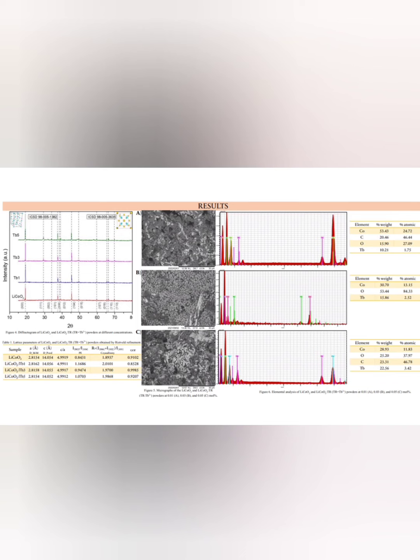According to the results obtained, X-ray diffraction was performed to analyze the structural properties of terbium-doped lithium cobaltate, obtaining planes attributed to layered materials with hexagonal structure and the space group R-3m. However, at a higher concentration of the dopant ion, an intermediate phase was observed, possibly generated by high temperatures at long residence times. A Rietveld refinement was performed and the values of the cells changed as the concentration of the dopant ion increased, to which the incorporation of the terbium ion in the structure is attributed. The goodness of fit showed that the values obtained are reliable.